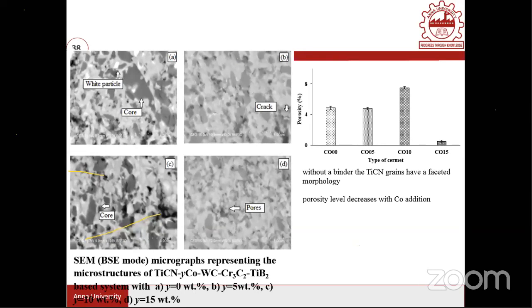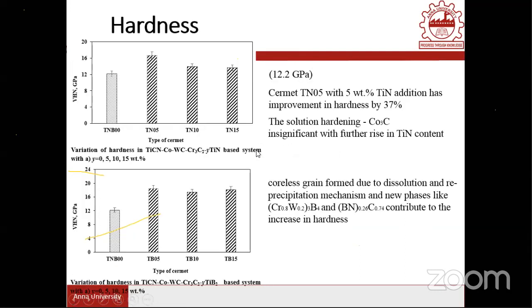So here the porosity level decreases with the cobalt addition, but here it is probably a data error in the Co10. Probably we have taken some microscope image where the porosity is there. If you take another area, probably it would be different. But here the general trend goes like this. There is a decrease in porosity level with increase in addition of cobalt value.